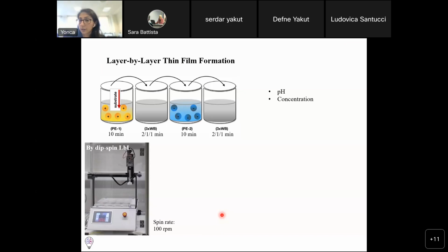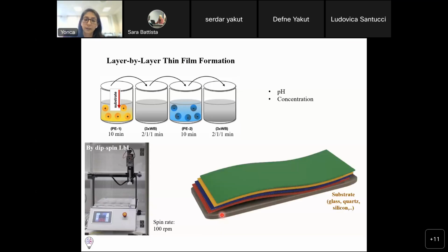Here I'll mainly check the pH and concentration of nickel phthalocyanine, not the supporting layers. What I mean by supporting layers is, this is the general scheme of the film. The bottom is the substrate. You can have anything you want: glass, quartz, silicon, metal, whatever you need. The red and the blue ones are actually adhesion layers. They are really, really thin layers. They are just needed to enhance the interaction between the upcoming layers and the substrate, but they don't play a role in the overall film properties.